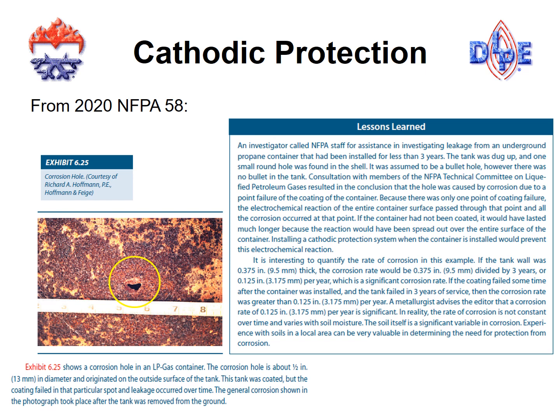This is a great example of what can happen if an underground tank is not prepared properly before it goes in the ground and gets backfilled. Again, this is where the importance of making sure those chips and those nicks and those scratches get touched up. This example took place not long ago, and basically what happened was this is an example of a tank that was installed and there was an imperfection in the coating. Maybe it was chipped or nicked during transport, but regardless, this approximately 1/2 inch in diameter hole was actually able to compromise this tank in a period of about 3 years. So in about 3 years' time, this tank went from being brand new installed in the ground to having a 1/2 inch diameter hole essentially burned through it from the corrosion.